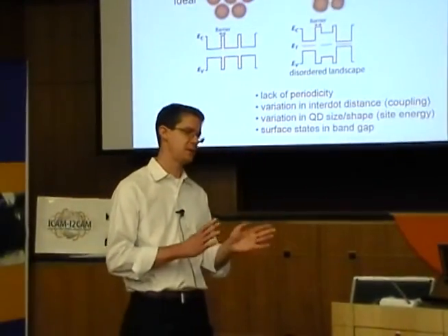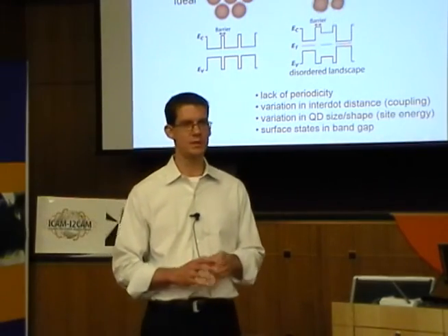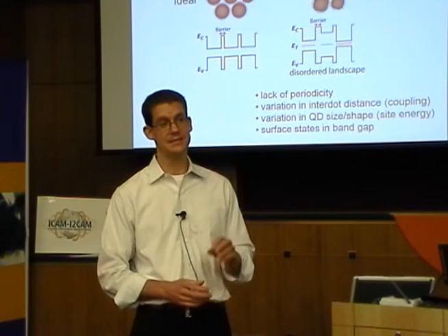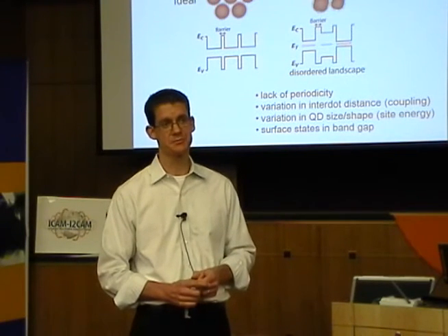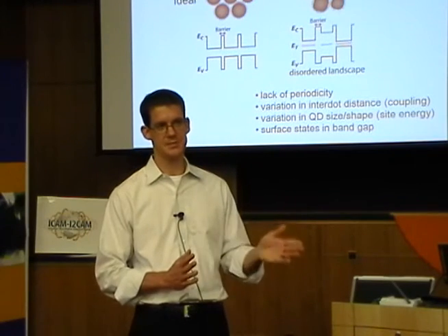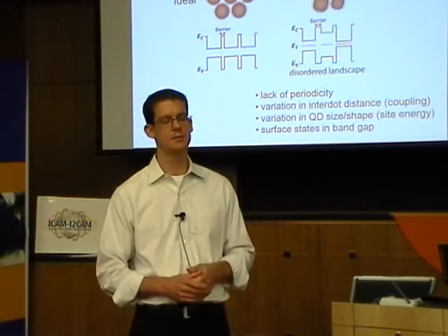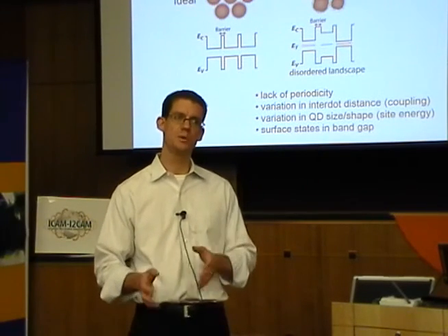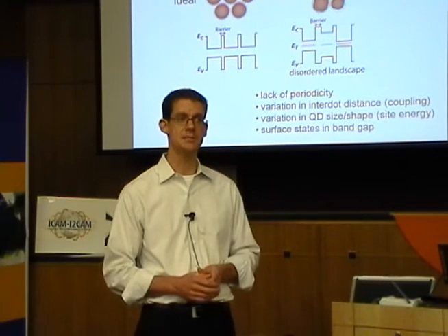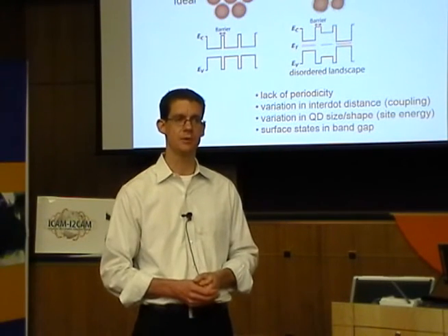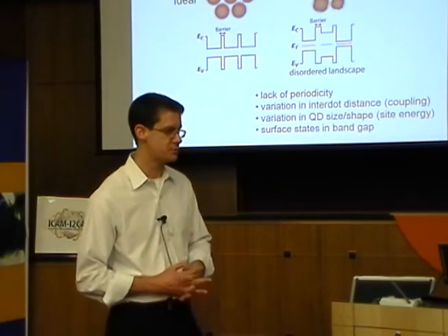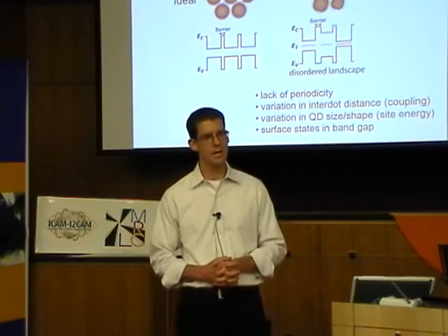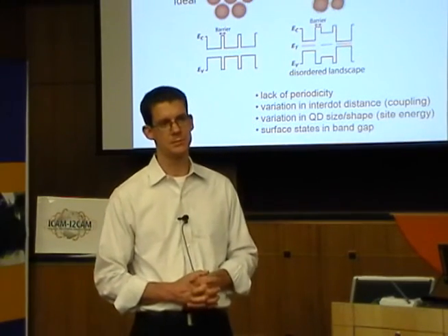Depending on how you divvy it up, there are basically 3 regions. There's the no confinement region, weak confinement, and then strong confinement. And it's dictated by the Bohr exciton radius. If your structure is smaller than the Bohr exciton radius, then you're considered strongly confined, and you should see pretty extreme effects. But in weak confinement, you should also see decent confinement effects. I don't know if there's a hard cutoff, but it might be three or four times the Bohr radius. Yeah, something like that.